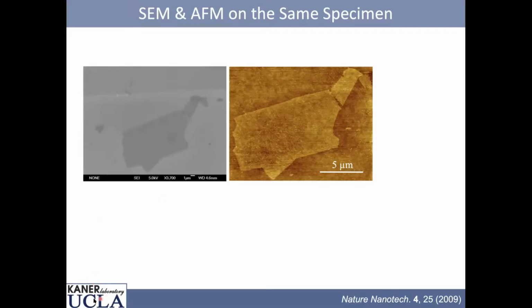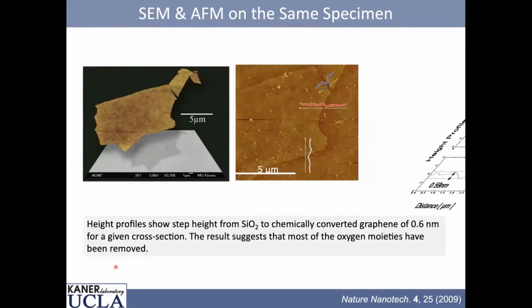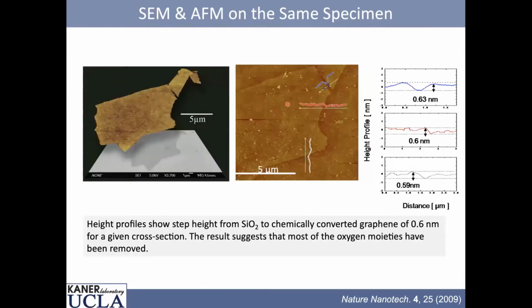All right. Now, we can actually do science with this. So we ran an AFM probe along white, along red, and along blue. And what you'll notice is as we go over this step height, each of these heights is about 0.6 nanometers. Now, it turns out the interlayer spacing in graphite is 0.34 nanometers. And if you multiply that by 2, you get 0.7 nanometers. So we know for sure that this is not 2 layers of carbon. It's actually 1 layer. Now, you may say, well, then why don't we get 0.34?